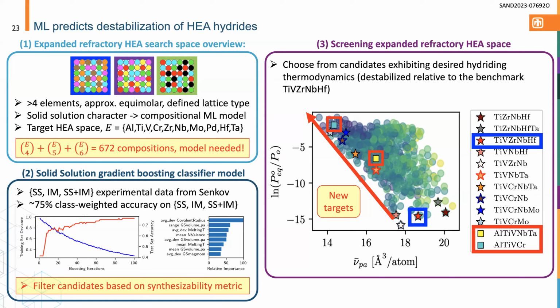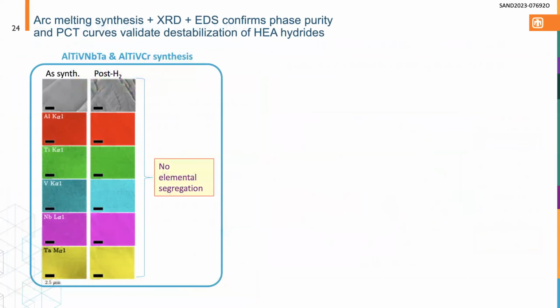So, you can screen all these new high-entropy alloys, and we chose 2 that span the range. You can see that the predicted range spans many orders of magnitude, so we just picked 2 in the middle. Also ones that included aluminum because it was just interesting. All right, next slide. So then we turn to our experimental collaborators who do all the synthesis. They do all the hard work, really. They do the synthesis, the characterization, and the PCT tests.